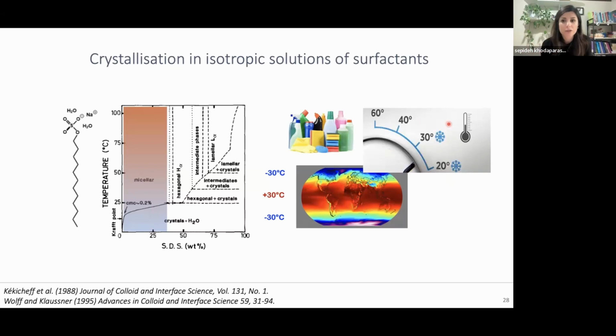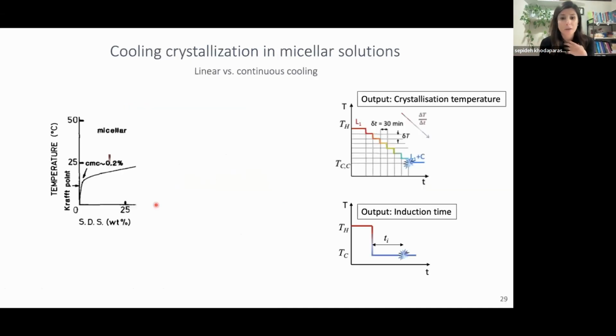And with the movement towards cleaning and washing, either a laundry or a dishwashing cycle at lower temperature, and especially these materials being produced and transferred across different temperatures, there is this issue that the majority of these formulations might go through these kinds of phase transitions. So there is that application that is quite important. But what I want to talk about is how do we actually measure this temperature. I'm going to talk in the context of crystallization, but it's quite similar to what happens during evaporation.